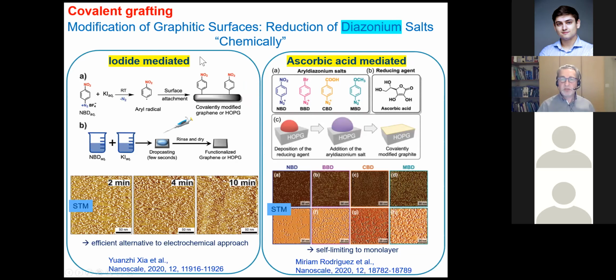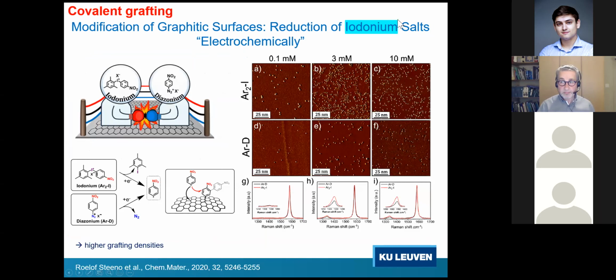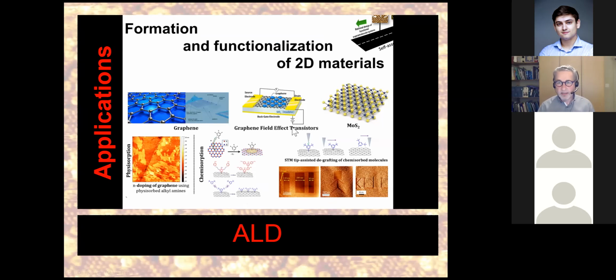I will now talk about something that we did more recently, in the sense that all of this was done electrochemically, but there are also good reasons to try to create these radicals chemically, by chemical reduction. Recently we showed that some iodide chemistry can be used, or that ascorbic acids can be used to activate the diazonium salts towards the formation of the aryl radicals. Also other systems, not diazonium but iodonium salts, can be used to create highly dense grafted systems. Okay, so we can graft molecules on a surface, and in particular, we can use scanning tunneling microscopy to visualize what we have on the surface.